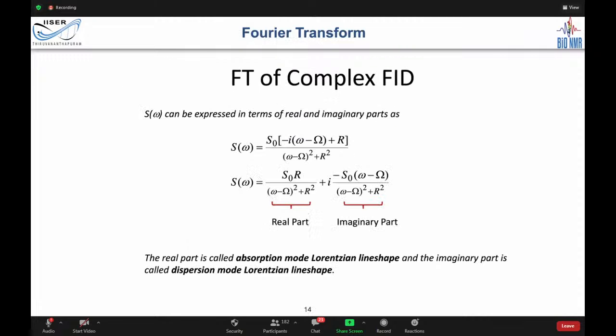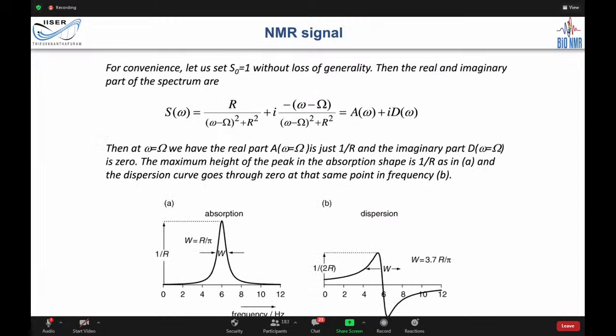I told you about Fourier transform. If you do a Fourier transform, you get a real part and you get an imaginary part. And the real part of the spectrum is Lorentzian. You probably have studied Gaussian, but this is the Lorentzian function. The difference is that the Lorentzian function is very sharp and tapers down pretty fast to 0. So you get sharp signals. What we observe, or actually draw, in NMR is the real part, not the imaginary part. The imaginary part we discard, but we need both real and imaginary for phase correction.